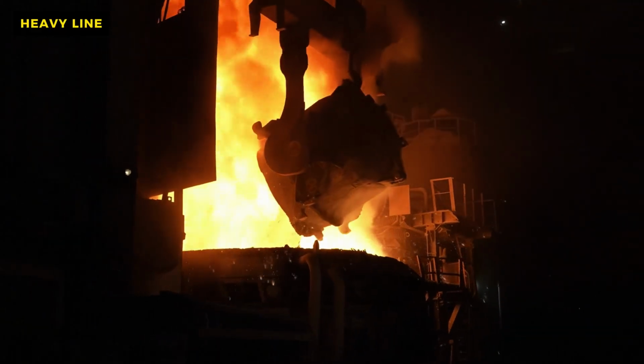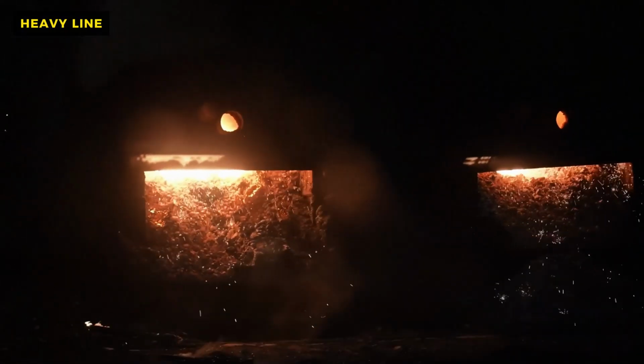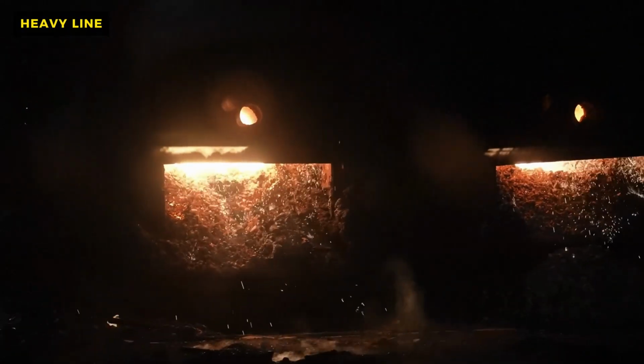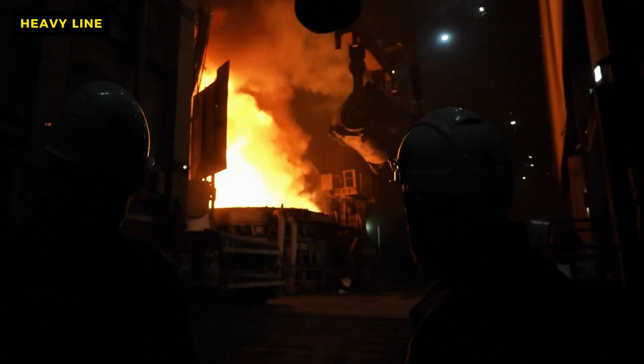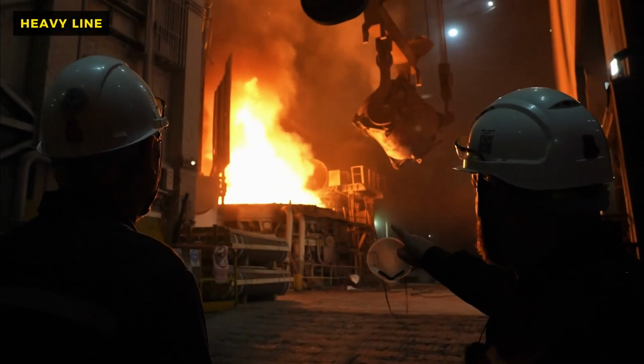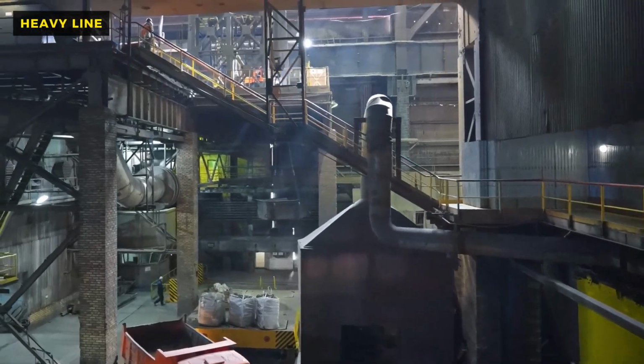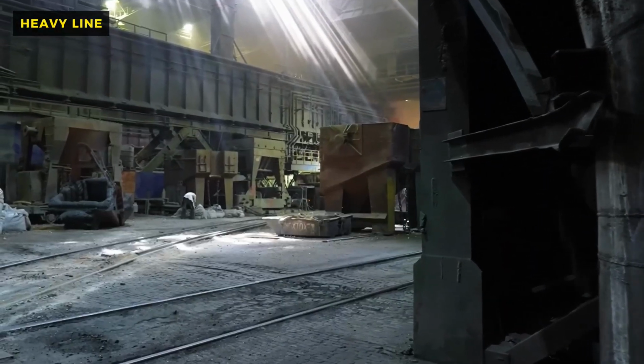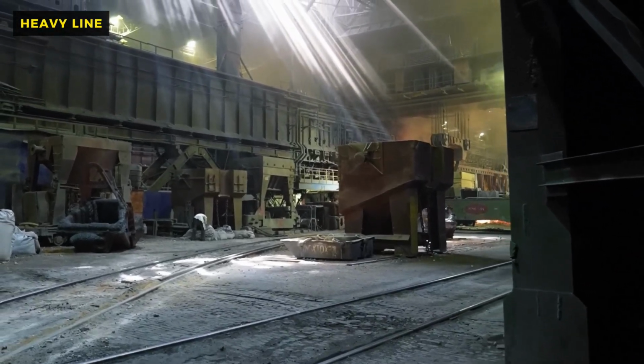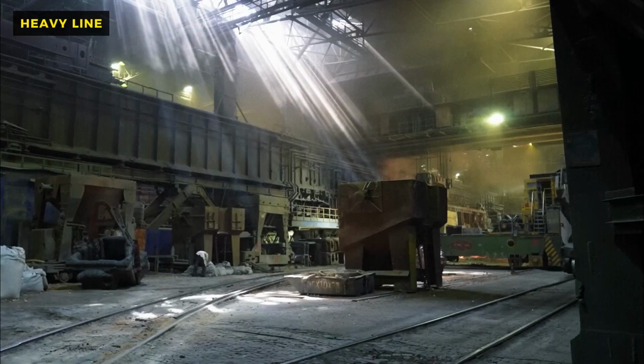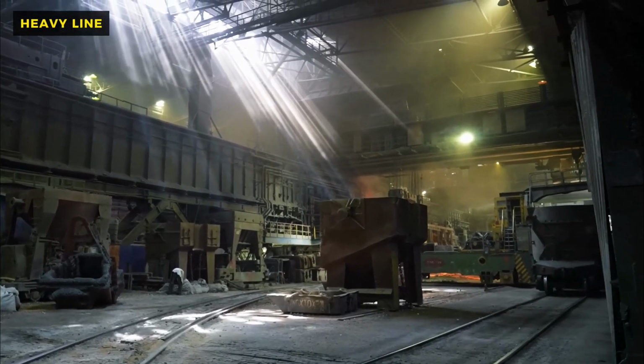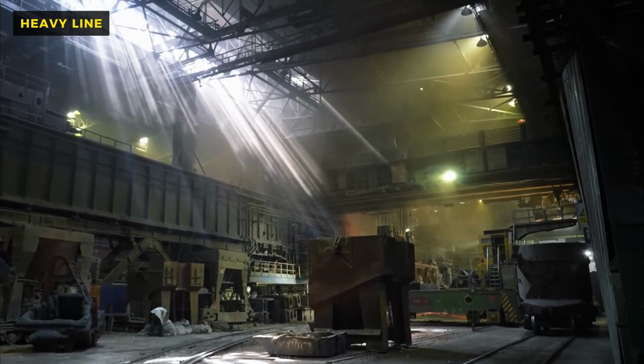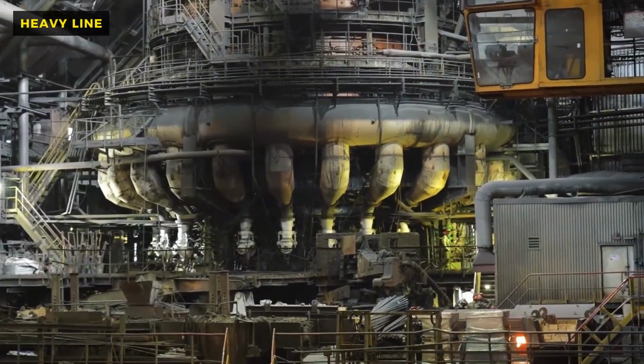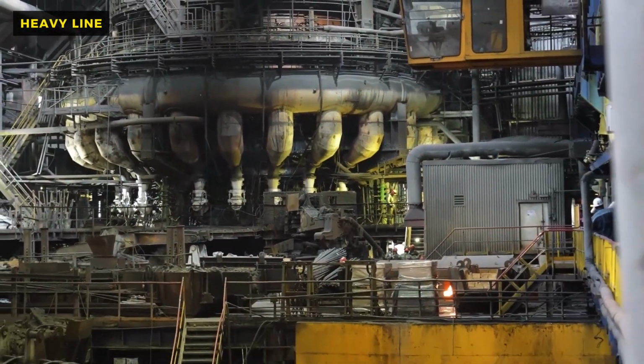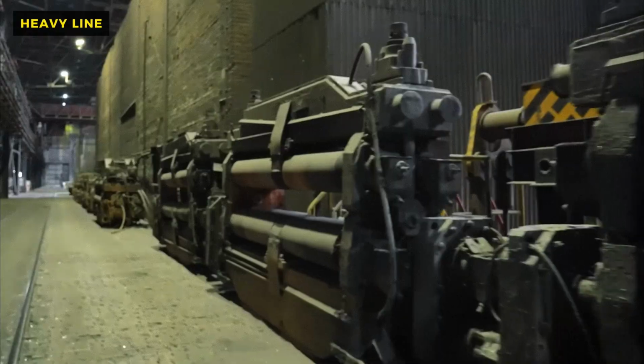After rolling, the plate passes through a controlled cooling unit where curtains of water quench the steel at precise rates to lock in the desired crystalline structure. The metallurgy is determined here. Cool it too fast, and it becomes brittle martensite. Cool it too slow, and it becomes soft ferrite. The goal is often a complex bainitic structure, tough enough to withstand the impact of an iceberg or the pressure